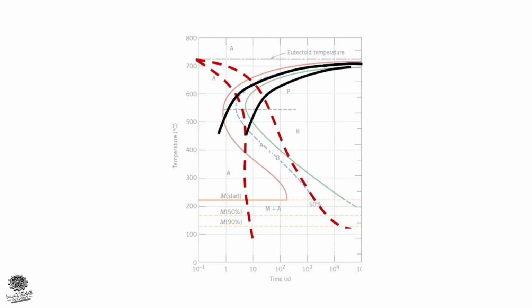But the CCT diagram. In this case, the sample is continuously cooled at a controlled rate. Compared to the TTT diagram, the nose of pearlite formation shifts to lower temperature. The CCT diagram provides unique information, such as during continuous cooling, phases like ferrite or bainite may form before martensite appears. Retained austenite can become enriched with carbon, which lowers the martensitic transformation temperature.